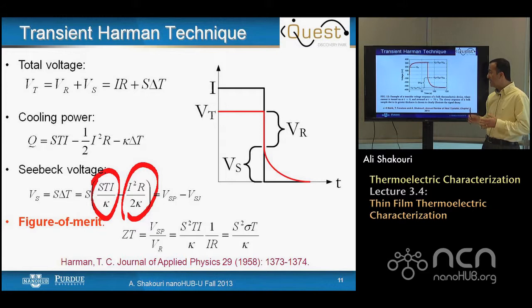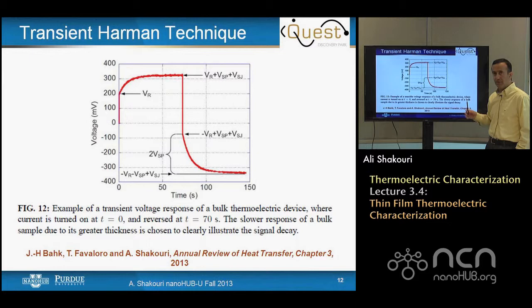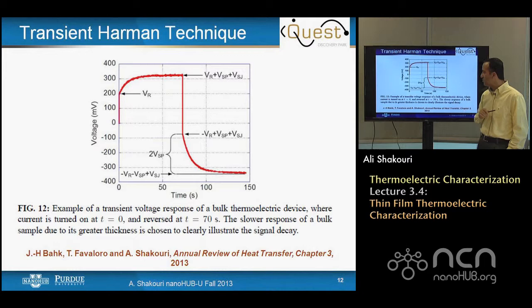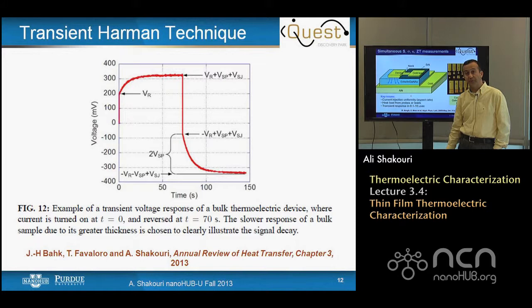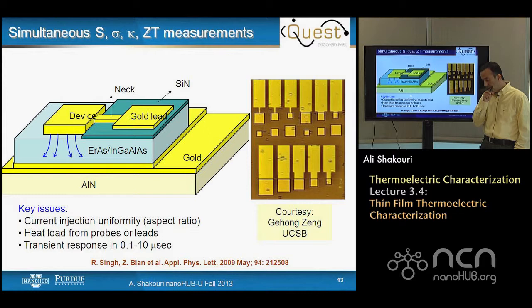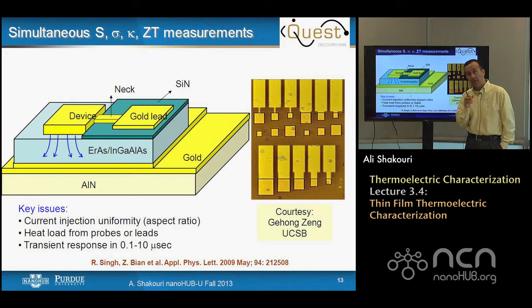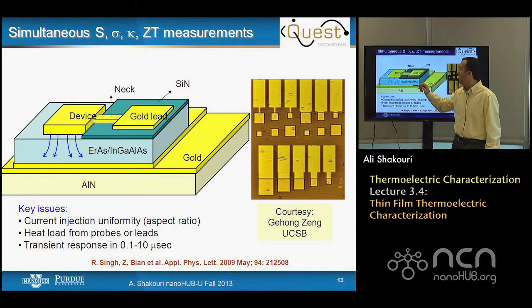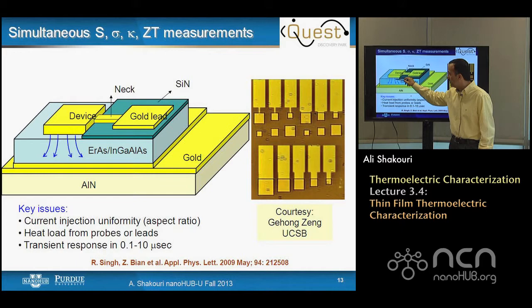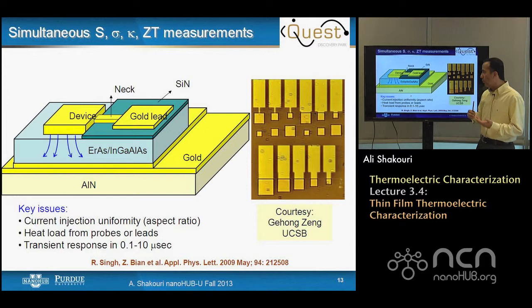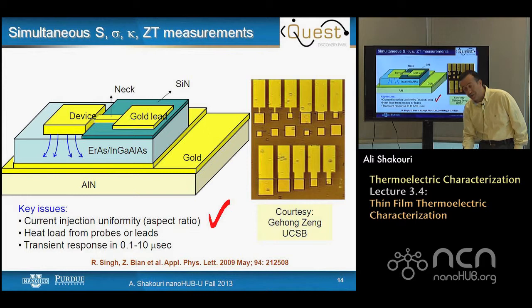By doing measurements at two polarities you can get the ZT of the material directly — dividing the Seebeck voltage component by the resistive component gives ZT. This was done for thick films since the 1950s, and some companies use it for inline characterization of thermoelectric modules all the time. The issue is that if you have a thin film and want to do the same Harman technique, the device becomes like a micro-refrigerator, and there are additional challenges.